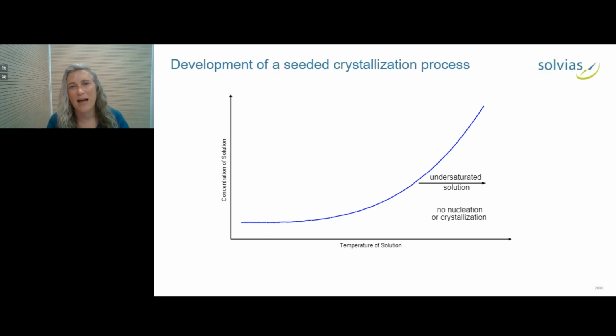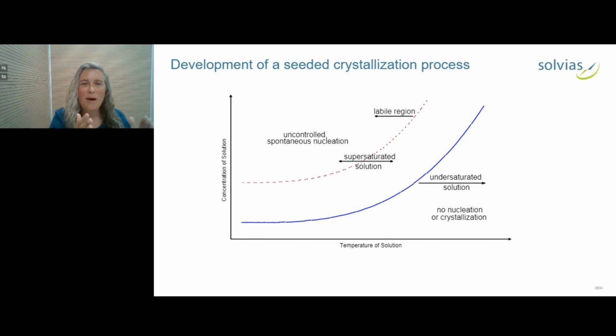And to the right side of the blue line, at higher temperatures, the system is undersaturated. So you're not going to have any crystallization. And if you go to the left of the blue line, so lower the temperature for a given concentration, you will have a supersaturated solution. And above a certain point, you get uncontrolled spontaneous nucleation. So this is called the labile region. And what you have in between these two regions is the so-called metastable region.